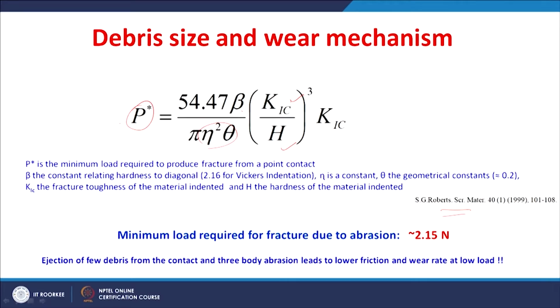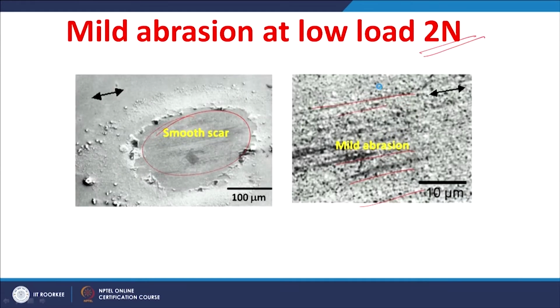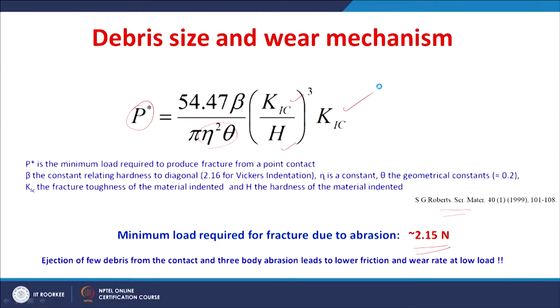The minimum load required for such an abrasion-induced fracture is around 2.15 Newton for the investigated ceramic composite. As we have seen, there is predominantly mild abrasion happening at a lower load of 2 Newton. So, it is quite possible that at a lower load of 2 Newton such a fracture is initiated, and then the removal of the material occurs by the abrasion.